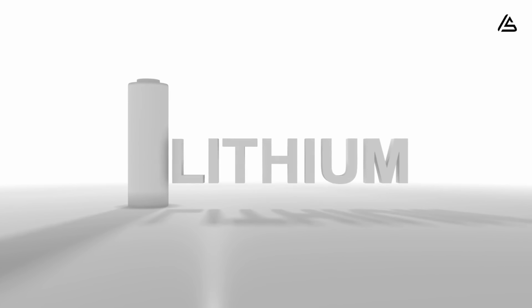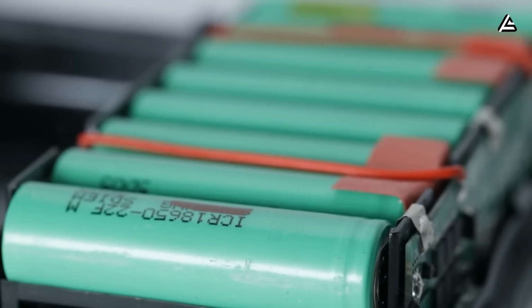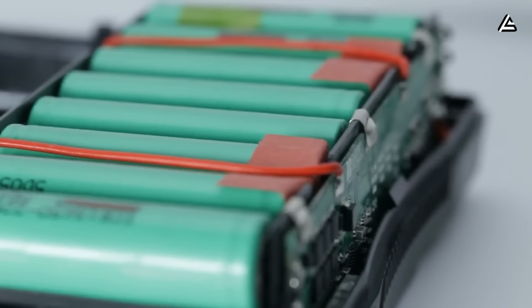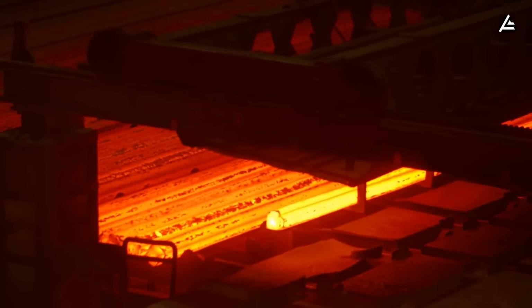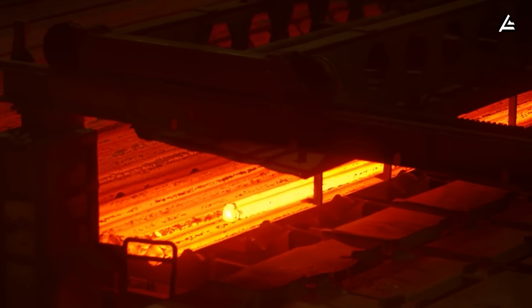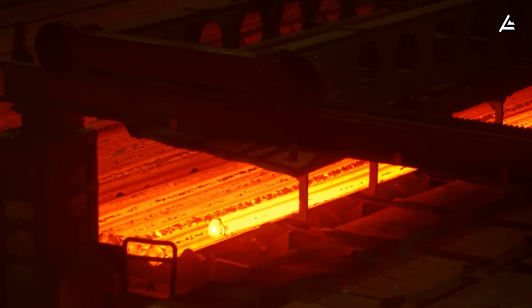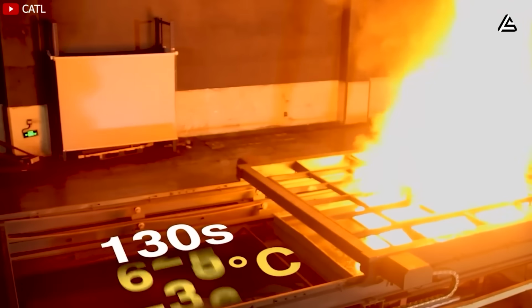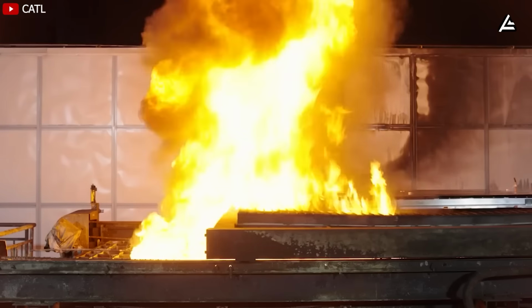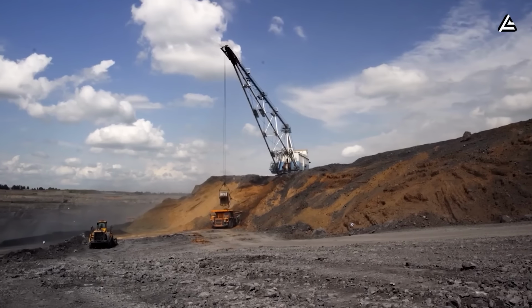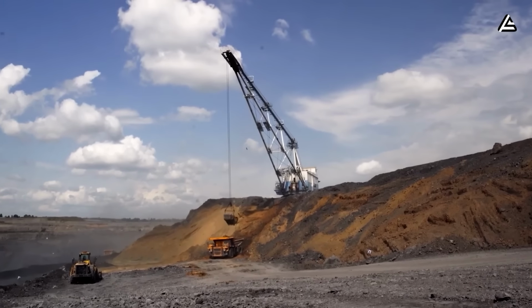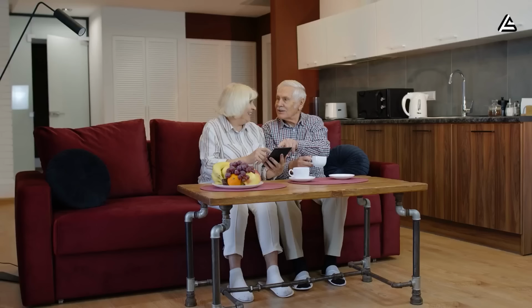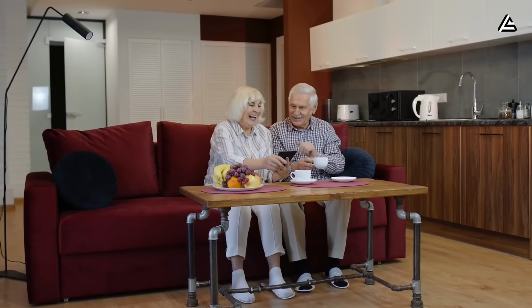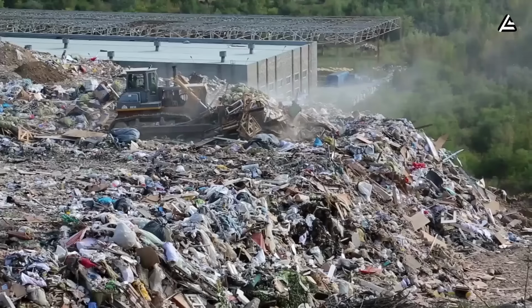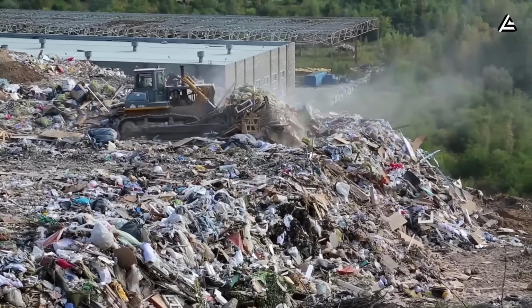When it comes to recycling, lithium-ion batteries have always been the weakest link in the EV chain. Recovering usable materials from them requires either pyrometallurgical treatment above 1,500 degrees Celsius or acid-based leaching using sulfuric or hydrochloric acid. Both methods consume huge amounts of energy and produce toxic residues. Extracting 1 ton of usable lithium consumes roughly 8 megawatt-hours of electricity. That's enough power for about 250 average U.S. homes for an entire day, and generates close to 3 tons of chemical waste.